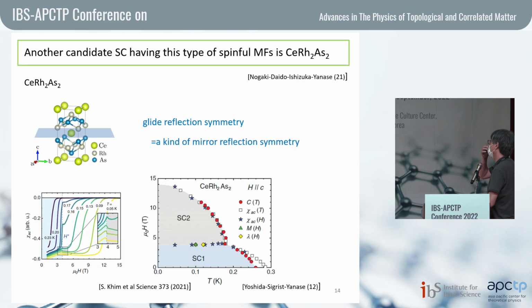And here I show another example, namely the recently discovered superconductor CeRh2As2. This is the crystal structure of CeRh2As2. Unfortunately, this crystal structure does not support mirror reflection symmetry. But instead of a mirror reflection symmetry, this crystal structure supports glide reflection symmetry, a kind of mirror reflection symmetry. By using a similar argument, we can conclude that if you can realize a glide odd superconducting state, we can expect spin-full Majorana fermions.